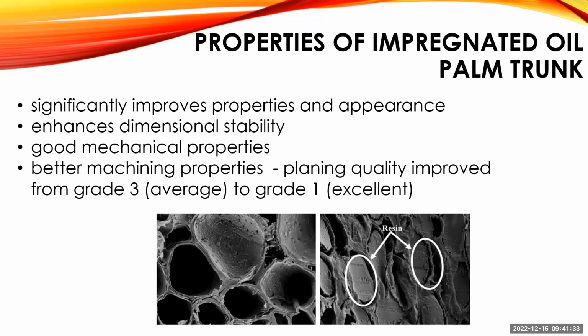Impregnation of PF into the oil palm trunk enhances dimensional stability, and the impregnated oil palm trunk also displays good mechanical properties. Apart from that, it also has better machining properties. In one study, it was shown that the planing quality improved from grade 3, average, to grade 1, excellent.